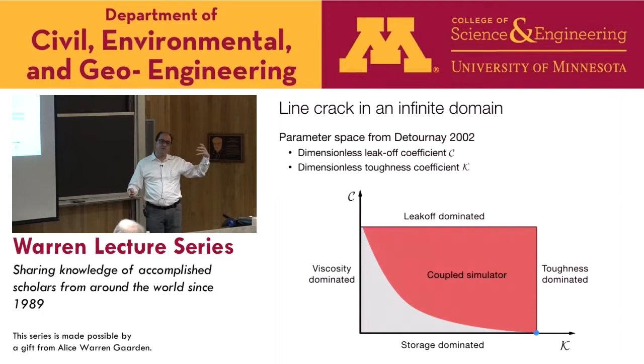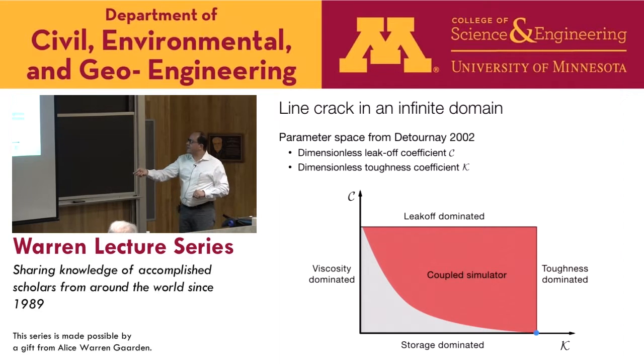The toughness has essentially no influence on the flow. This is something that is very challenging for us because all the representation of the fracture system comes from the mechanics, comes from solving the Griffith problem. So if you tell me that in Griffith fracture mechanics the toughness has no impact on the geometry of the reservoir, I don't know how to recover my phase field. So this edge is definitely something we cannot do. The storage-dominated regime, that's the situation where, for instance, the permeability of the reservoir is essentially 0, is quite challenging because we put a lot of work into trying to replace the flow in only the fracture with a flow in the entire reservoir. So in this regime, we actually have a problem where the equations of the fluid are not defined in most of the domain. Maybe we could fix that, but you know. So this is more or less the range of what we can simulate.